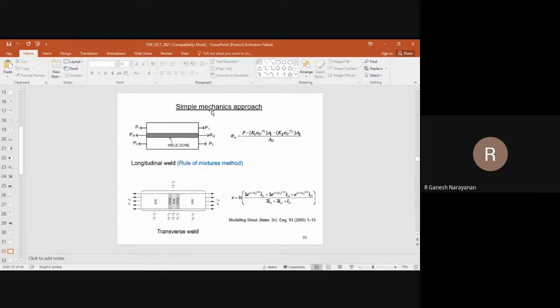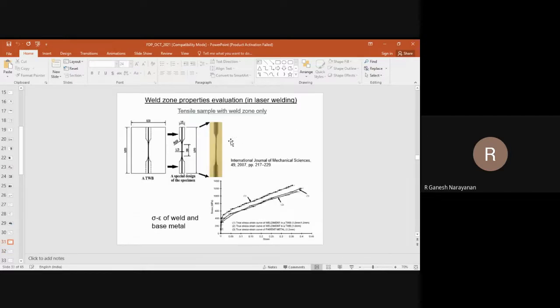Simple mechanics approach is also possible. Suppose you take a longitudinal weld like this and you are doing tensile testing. Load sharing principle is possible, isn't it? The total load will be equal to P1 plus P2 plus PW. Correct? That can be converted into a stress strain behavior, and you get a simple equation between sigma W and epsilon W. These are variables. K1, n1 are the strength coefficient and strain hardening exponent of base material 1. Similarly K2, n2, you know these properties. Area can be evaluated. P is the total load which is given by the machine. So you can substitute all these properties, and for different values of epsilon W, you can get different sigma W. That will give you the stress strain behavior.